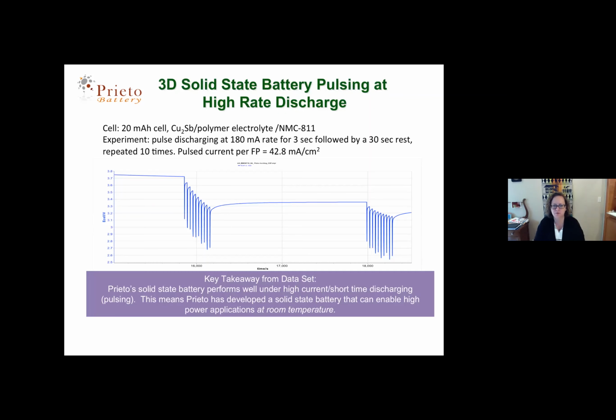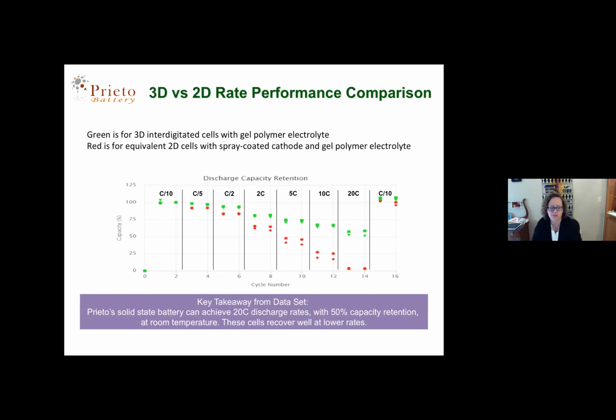So this battery does handle high current discharge. In this experiment, this is a small cell, it's a 20 milliamp hour cell, but our Cu2Sb anode, our polymer electrolyte, and an NMC-811 as a high voltage cathode. We pulse discharged 180 milliamps for 3 seconds, followed by a rest. And this battery can handle that repeatedly. So we did 10 pulses and then a rest and then another 10 pulses. So this was really important for Stanley Black & Decker to be able to demonstrate that this battery could handle high discharge currents without shorting, without having sort of a leaky current, but more importantly, to be able to do this at room temperature.